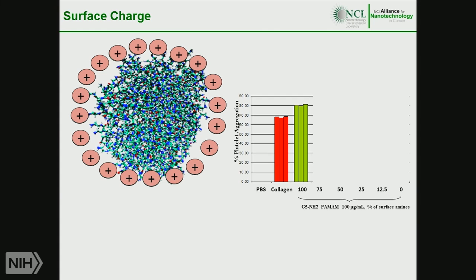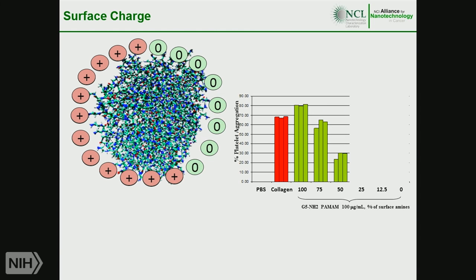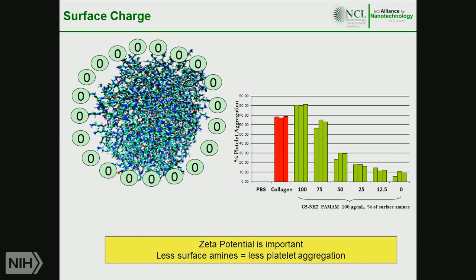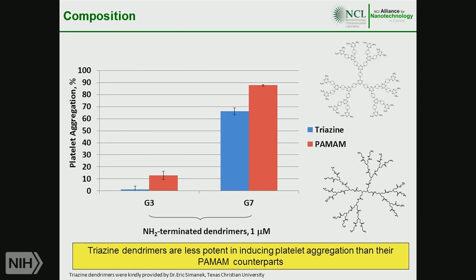And he used chemical modification to mask 25% of the particle surface amines, then another 25%, and another 25%, and so forth, till no surface amine was left. And as you see, as we decrease the percentage of surface amine, the reactivity of this particle with platelets decreases. So if we want specifically to induce platelet aggregation, then we want to use this particle, right? Because we know that it activates platelets and is biologically reactive. But if we intend to use this particle in biological applications and inject it in animals, this material would be toxic. But by masking surface amine, we make it more biocompatible and less toxic.